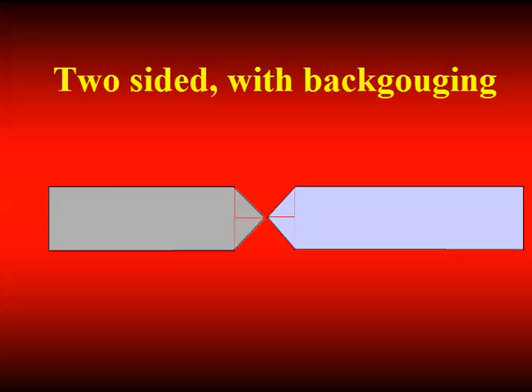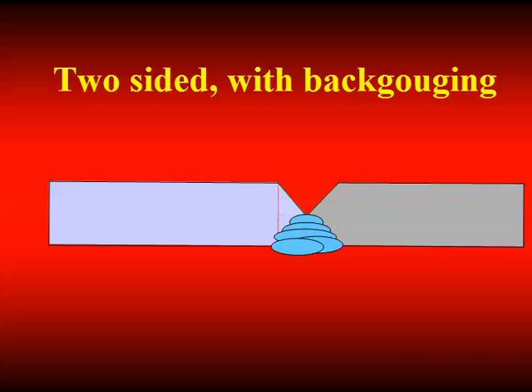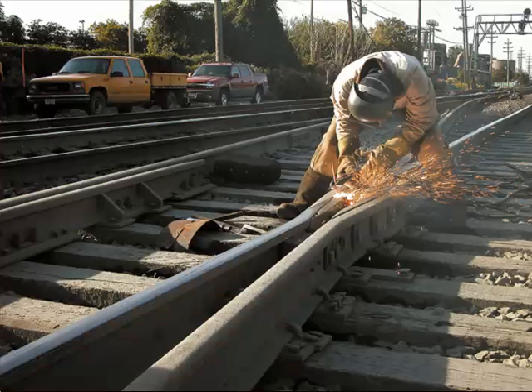When we go to double-sided joints, we always have a back gouging operation with our pre-qualified procedures. So you put in the root pass and weld up one side or a portion of that one side, flip the plate over, and then you grind into that previous bead or air arc gouge into that previous bead until you know you're into sound weld metal, and then the second side is welded up. So this is showing that the root pass from the opposite side has been removed so that I know I have sound weld metal. A common process used, I've previewed this to you already, is air arc gouging.